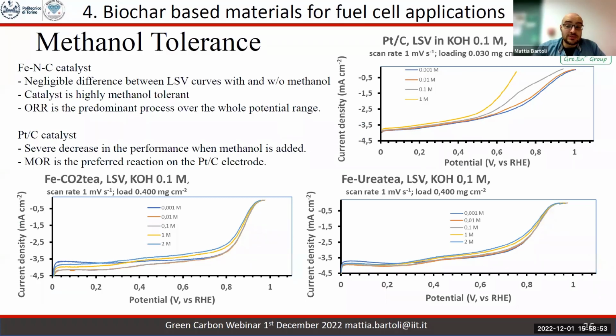The real strong point in our case was the methanol tolerance. As we try to figure out how to solve the methanol problem, or at least approach the methanol direct fuel cell by using biochar, what we saw is that both engineered biochar catalysts were far more stable than platinum in methanol. What does it mean? It means that they did not lose any activity over time, and they could be cycle after cycle recharged and reused. So our engineered material could match the performances of platinum carbon over time, because when platinum lost activity, ours remained the same. So it's a thing that should be considered.